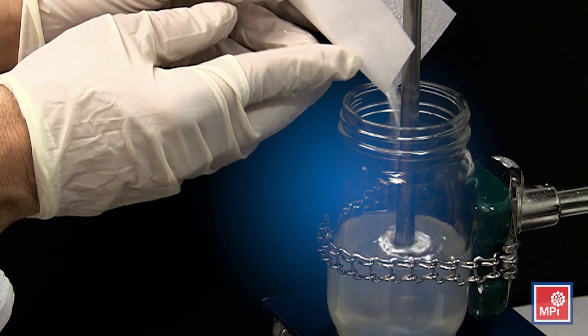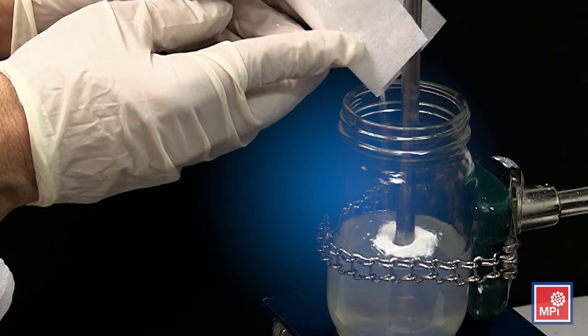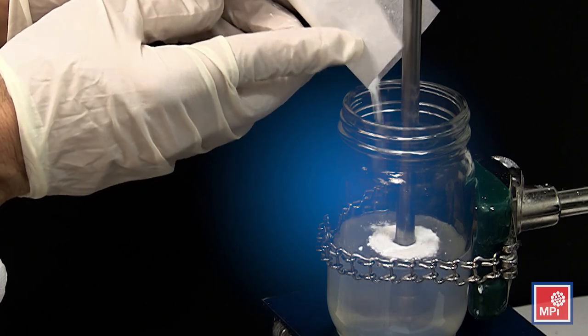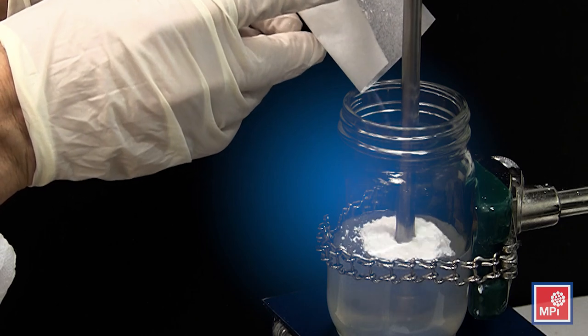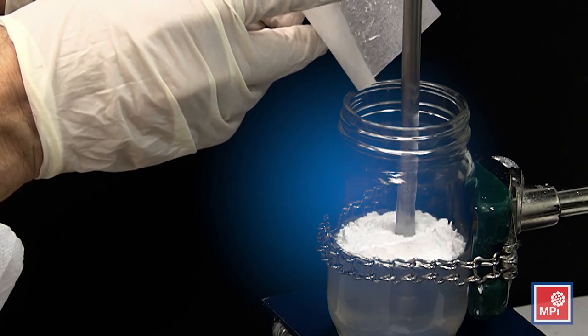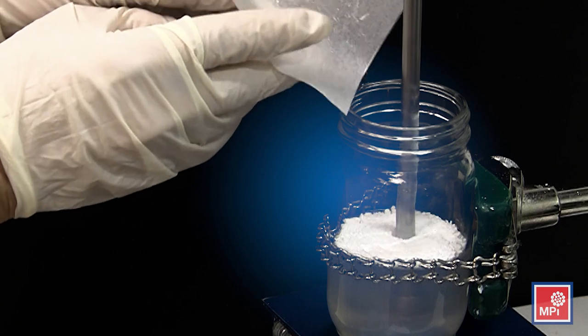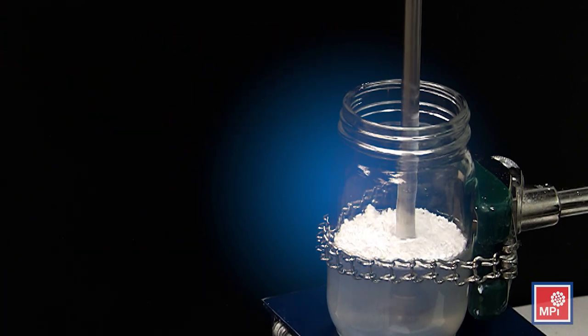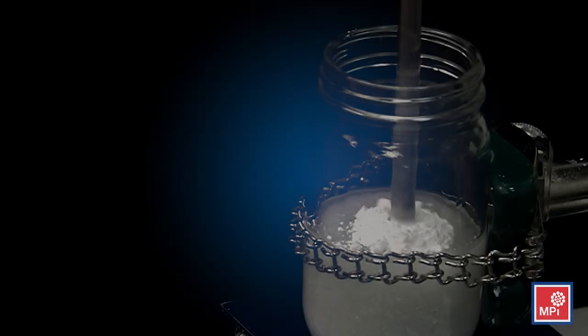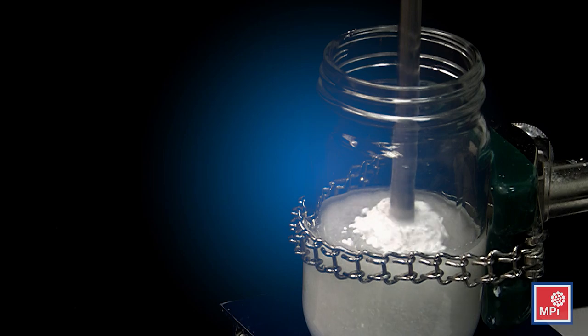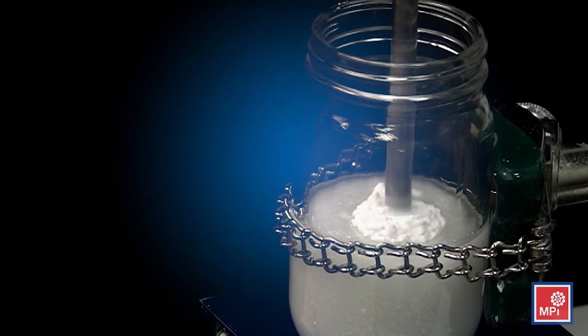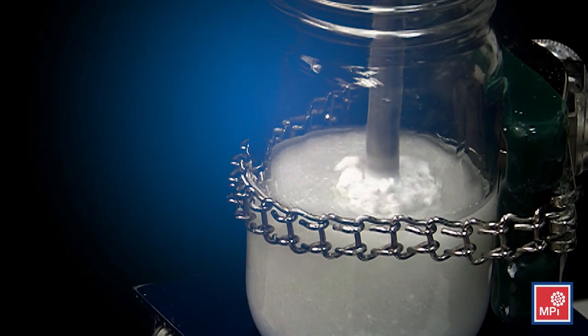We don't recommend adding the dry powdered wax directly into the final waterborne formulation, as this would typically lead to poor wetting and insufficient dispersion. Notice how difficult it is to properly wet and separate the agglomerated wax particles, even with high shear.